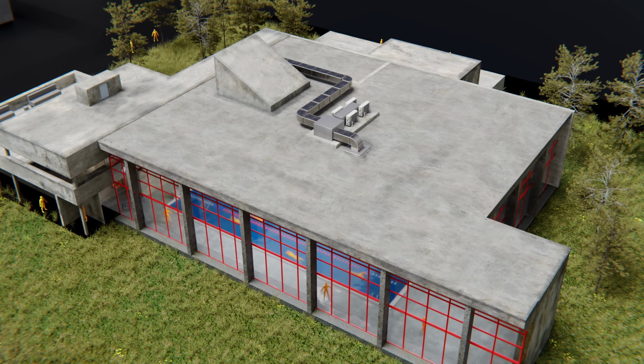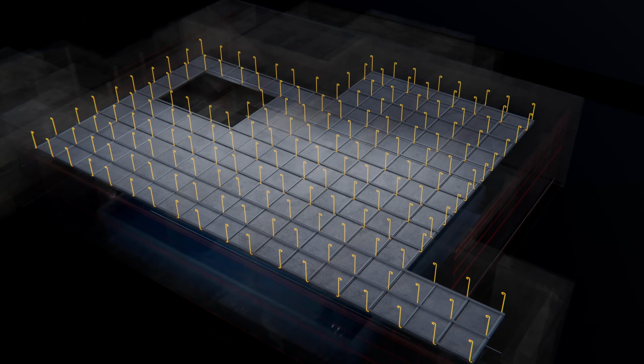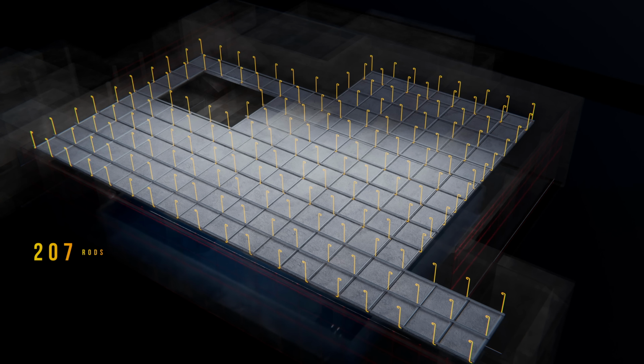It was only after the collapse that investigators discovered the extent of the damage. Of the 207 rods, 108 fractured during the collapse, with 94 of those showing evidence of chloride-induced stress corrosion cracking.